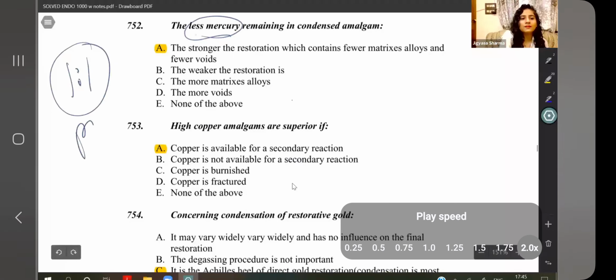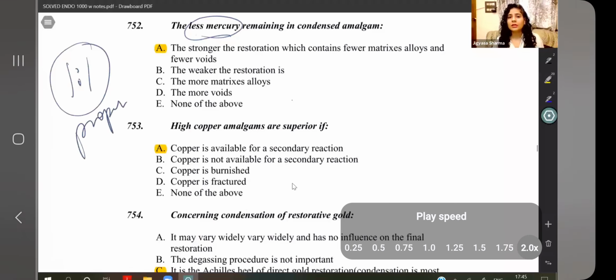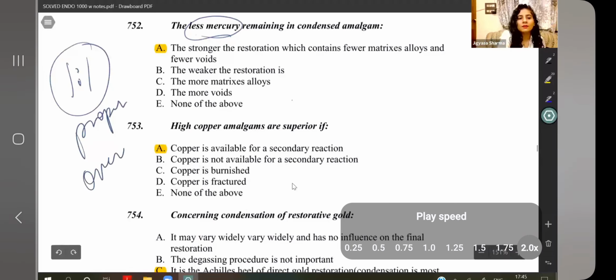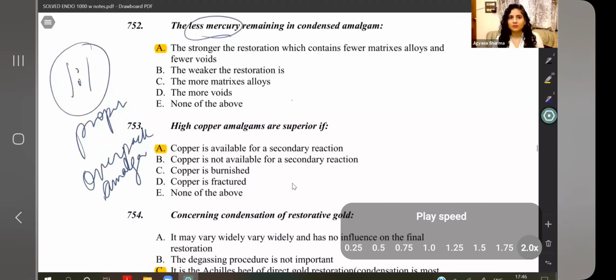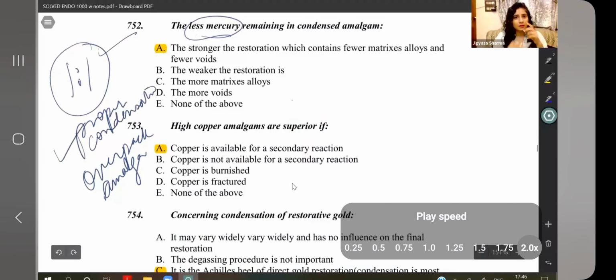And the next is proper condensation, by which you make sure that the mercury rich layer reaches the top, and then you overpack your amalgam, so that that mercury rich layer is removed while carving. So that's how you ensure that the ultimate amalgam restoration is as low in mercury as possible. First the mixing ratio, then proper condensation so that the mercury rich layer comes at the top, and then overpacking of amalgam so that the topmost mercury rich layer is taken off by your carving, and the final condensation. So ultimately the restoration is stronger, containing fewer matrix alloys and fewer voids.